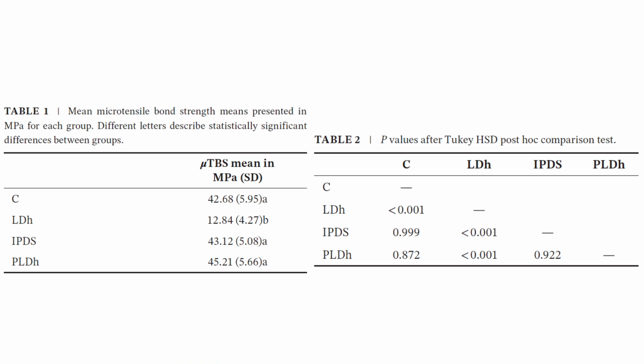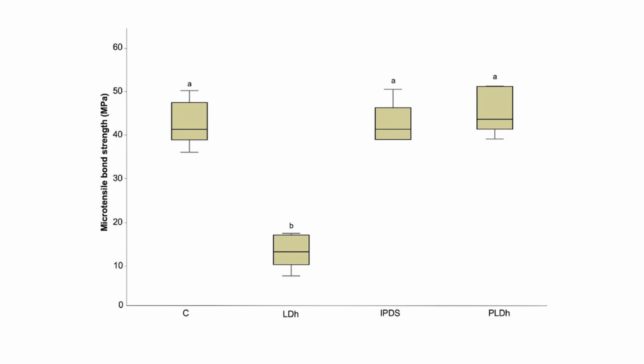For the results, the highest bond strength values were found in the control, pre-endodontic dentin seal, and dentin seal after ultrasonic preparation groups, without statistically significant differences among them. The lowest value was found in the late dentin sealing group, statistically different from the other 3 groups. This box plot showed that when dentin hybridization occurs before exposure to the endodontic chemical substances involved in endodontic treatment, there was an increase in bond strength of 238%. Similarly, there is a 252% increase if the dentin is re-prepared after endodontic treatment and then hybridized.